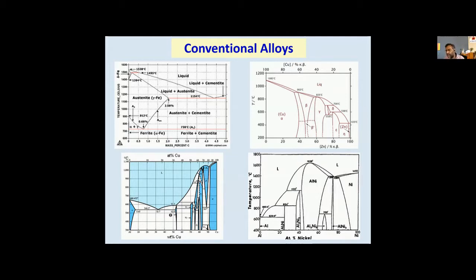If you look at all these phase diagrams, there is something in common. Initially when you add the solute to a solvent — for example, carbon to iron — to some extent carbon dissolves in iron. The moment you add more and more carbon, it precipitates in the form of a compound called cementite. Similarly, if you look at copper-zinc or aluminum-copper or aluminum-nickel phase diagrams, as you go to the center of the phase diagram, you always find compounds. People know that compounds are very brittle. That is the reason why most alloys developed conventionally avoided having 50% of one element and 50% of another — you typically end up with brittle compounds.